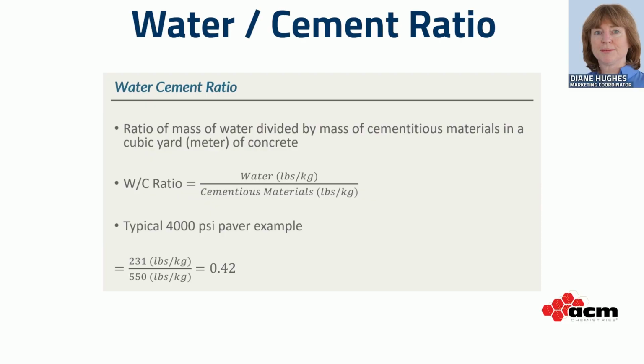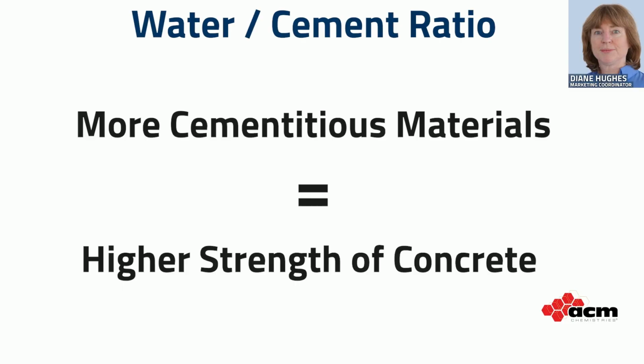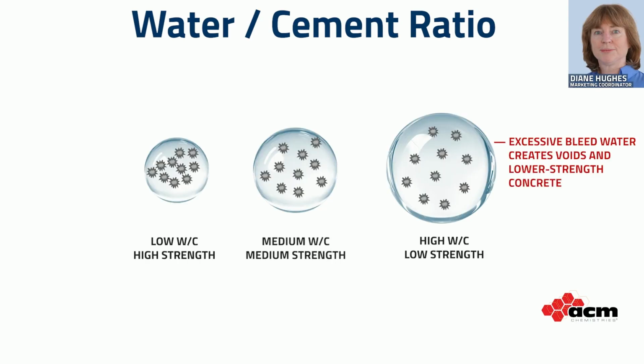Workability and strength are two fundamental performance properties for slump concrete. Same as in dry cast, strength is mostly influenced by the amount of cementitious materials, and all other things being equal, more cementitious materials will generally lead to higher strengths. In wet cast, it is possible to add more water than is needed to hydrate the cementitious particles, and this leads to a high water-cement ratio. When too much water is added, the excess water will bleed out, leaving voids and lower strength concrete behind.